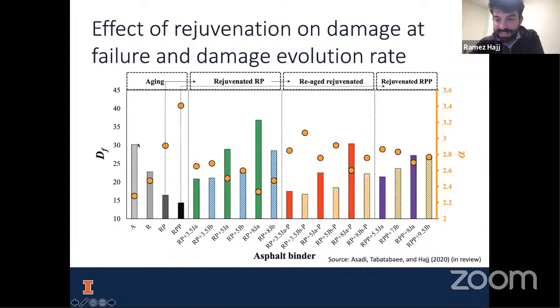In some cases, it even passes the original material, which is why I say that rejuvenation is a little bit of a misnomer. It's not necessarily the correct name for the mechanism, because in some cases, when we add so much rejuvenator, we are making the material properties even better than the original material properties. What this means is that this is not a restoring of the original properties, it's just a softening. And we can see that when we re-age it, we are able to keep some of those properties. Finally, we can do many cycles of rejuvenation and maintain almost the same properties as the original. This is quite powerful because we can recycle the material, let it live another life in the pavement, and then recycle it again with the help of rejuvenators.